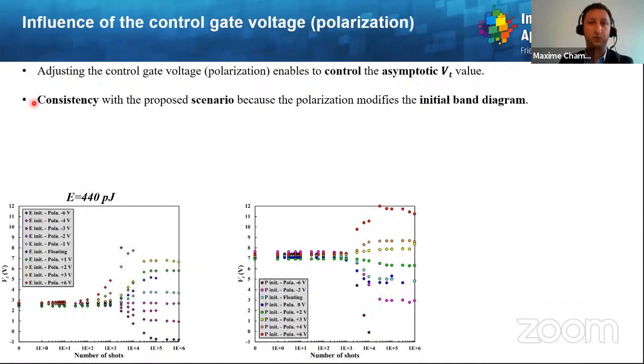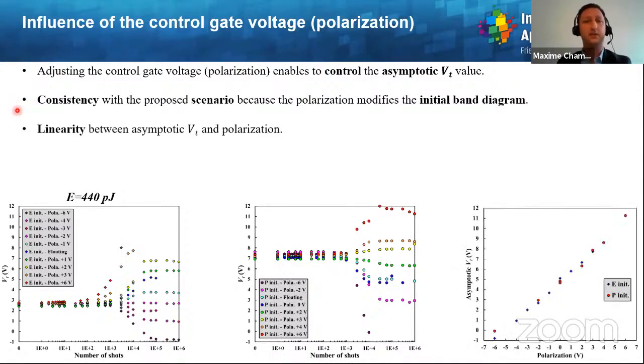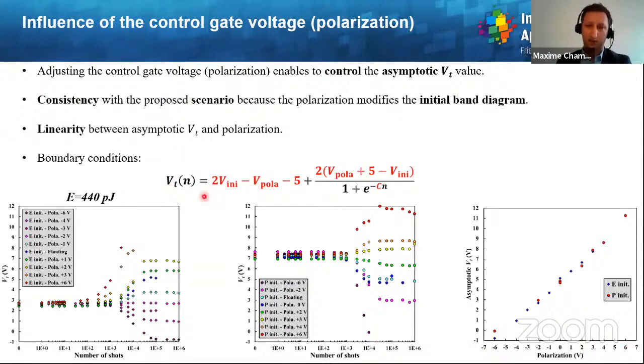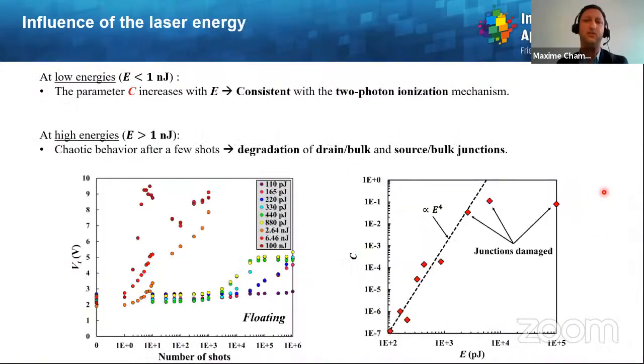This is consistent with the proposed scenario because the polarization will modify the initial band diagram. And we also observe the linearity between the threshold voltage and the applied bias. This allows us to determine A and B in the sigmoid curves, so two of the three free parameters, which are related to the boundary conditions. So now we just need to evaluate what C is and how it can be related to the laser parameters.